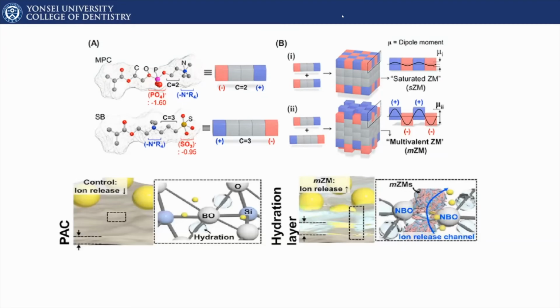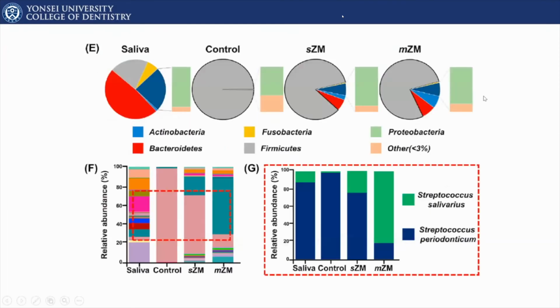So this phenomenon has been confirmed, and we try to find out what kind of mechanism studies we can do further to find out this interesting phenomenon. But another interesting thing is the microbiome results. As you probably know, saliva is full of different microbiomes. When they are exposed to dental materials like zinc-containing glass ionomers, the microbiome changes dramatically.